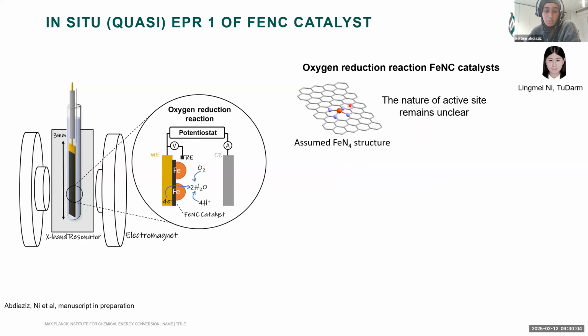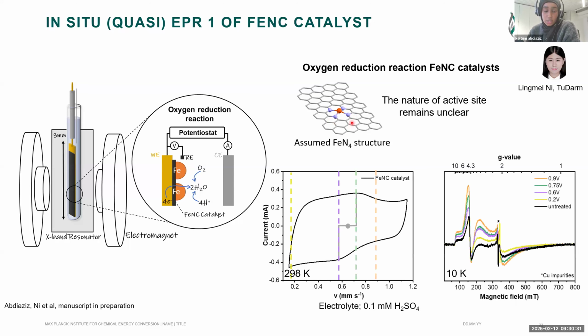I forgot to mention, but one thing about this catalyst is that to get a very active catalyst, we have to pyrolyze all the different precursors at a very high temperature. So it's not a very clean catalyst. Trying to disentangle all these different iron species is very difficult, and this is the main aim of our application. And so that's what we did.